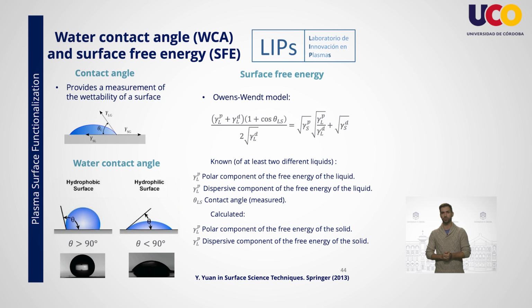A parameter which is related with the contact angle is the surface free energy. Interactions between solids and liquids are important in many processes, as they determine the adhesion between the two phases. While the measurement of the contact angle on its own indicates the wetting of the solid by a particular liquid, the surface free energy represents the quantitative measure of the intermolecular force at the surface, which is independent of the liquid used. So, by knowing the surface free energy of the solid, one can predict the behavior of any liquid on the surface. However, surface free energy cannot be directly measured.